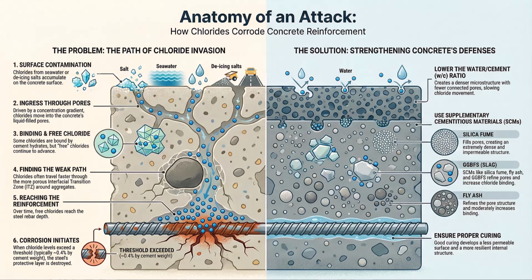This combination of strict material inputs and verifiable performance targets is the only way to ensure these structures survive the Gulf's unparalleled severity. This deep dive really shows the remarkable complexity of building long-term infrastructure in the GCC. Right. To synthesize the failure mechanism, you have the sustained, accelerating heat of the Arrhenius effect. You have the extreme concentration of chlorides from both seawater and groundwater, and then the persistent saturation that ensures diffusion is always the dominant force. This unique stack-up just ensures that standard OPC structures are going to fail rapidly.